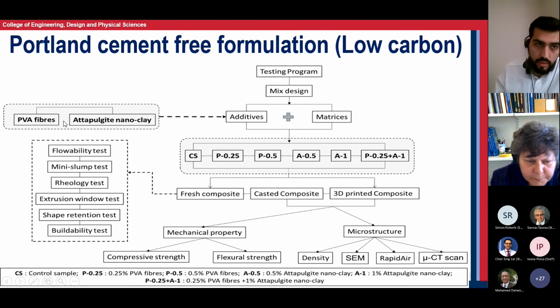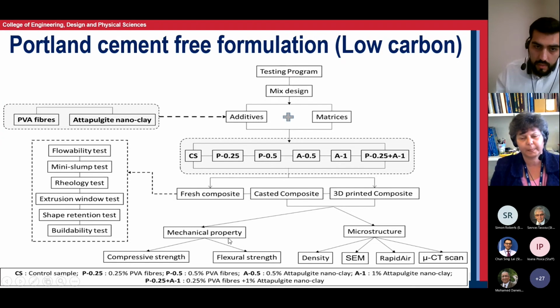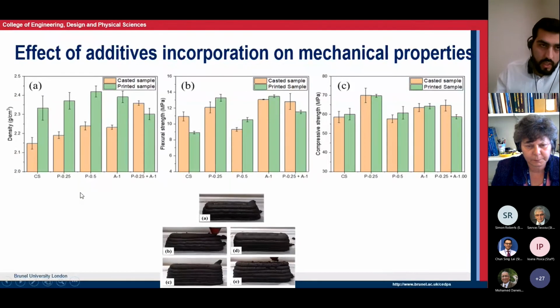We use these two important materials, attapulgite and PVA fibers, to help us increase the flexural strength, the 3-point bending test. We studied the fresh properties, so as concrete is mixed, immediately after mixing. We also did some casting of the composite in order to have a benchmark. And of course, we 3D printed the samples. We investigated the mechanical strength and the microstructure in order to be able to draw some conclusions. The mechanical results were very encouraging.